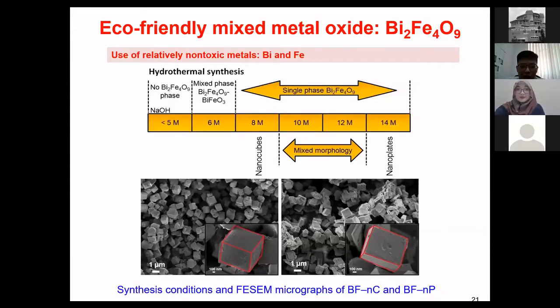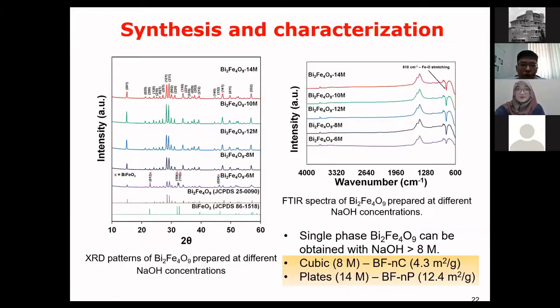And the morphology that we have, you can see here, is controlled by hydrothermal synthesis. If you look at this, we control it using sodium hydroxide concentration. If you use about 8 M of sodium hydroxide, you get a cubic-like morphology. But if you increase it up to 14 M, you have this nanoplate-like morphology. So this is significant because if you have nanoplate morphology, the surface area will be higher compared to when you have a nanocube morphology.